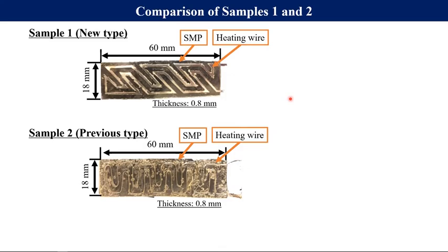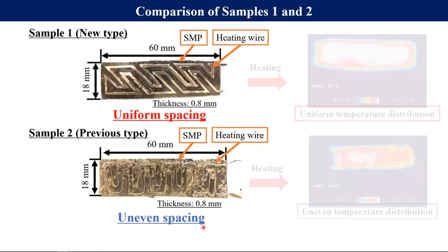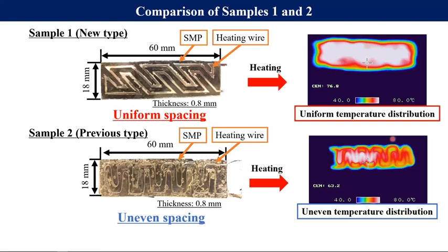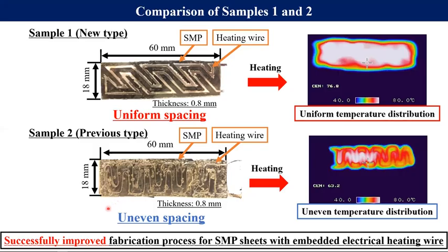So this is a comparison of samples 1 and 2. I'm going to call sample 1 the new type and sample 2 the previous type. Visual inspection shows that the spacing of electrical heating wires in sample 1 is more uniform than sample 2. And here's an image of each sheet when heated. It can be seen that the temperature distribution of sample 1 is more uniform than that of sample 2. And based on these results, we found that the fabrication process for SMP sheets with embedded electrical heating wire was successfully improved.